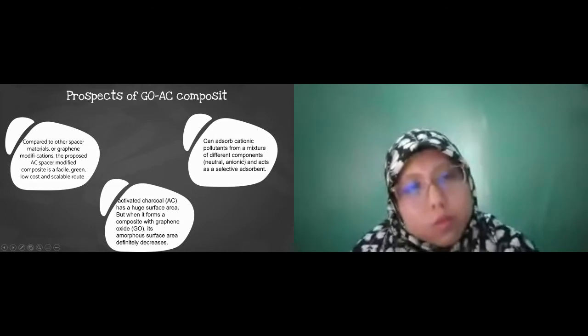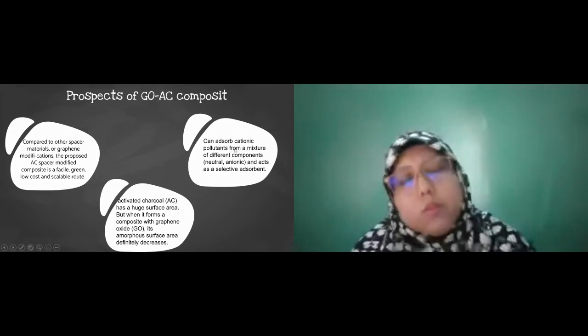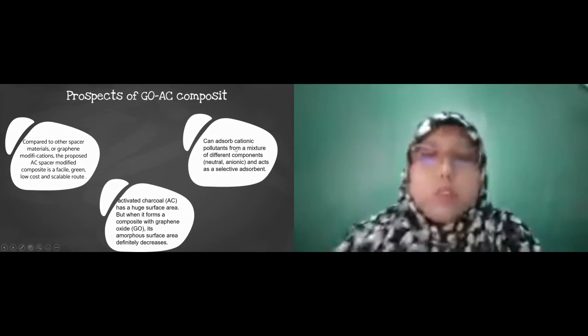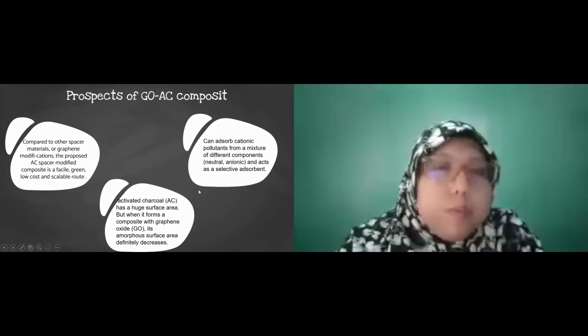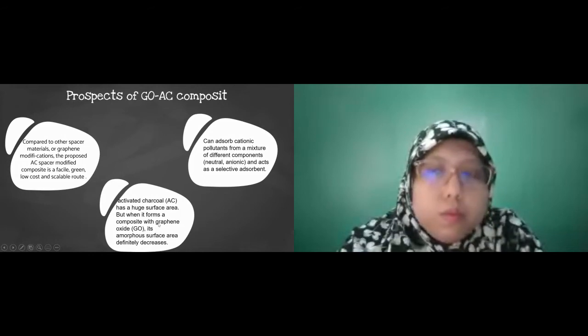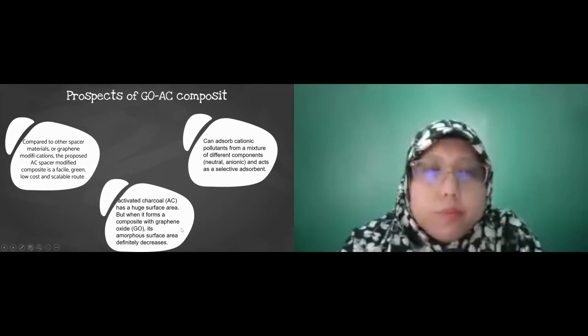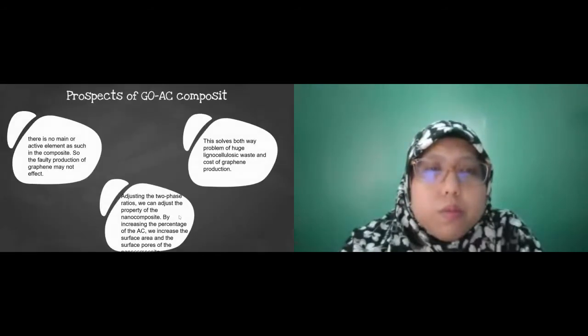Also, selective adsorption is happening here. As I said, it takes the cationic dye and cannot take the anionic dye yet, so we can work on that too. Here, activated charcoal has a huge surface area, but as I said, when it is composed with graphene oxide, the area decreases. That is as well a good sign, because then the composite is able to hold antibiotics and very small particles as well. So it will be a very good adsorption. And in the composite, both are ruling, so no one is dominating.